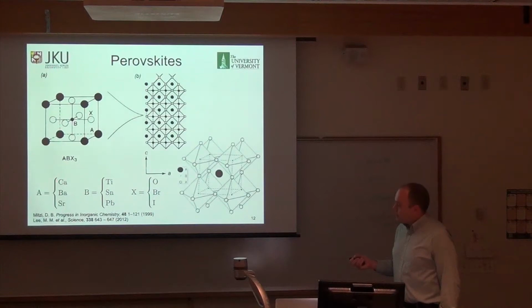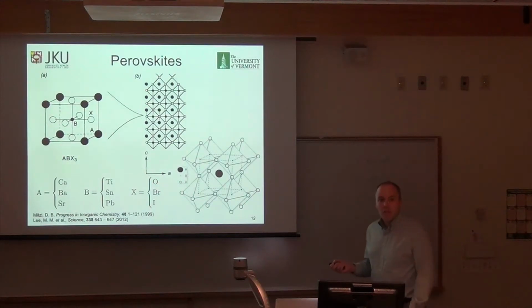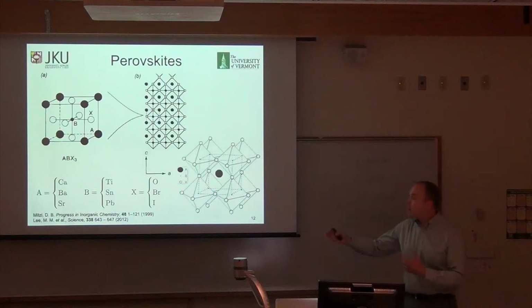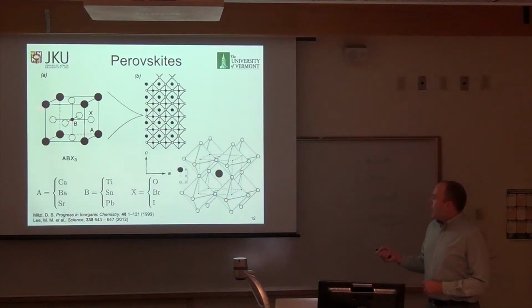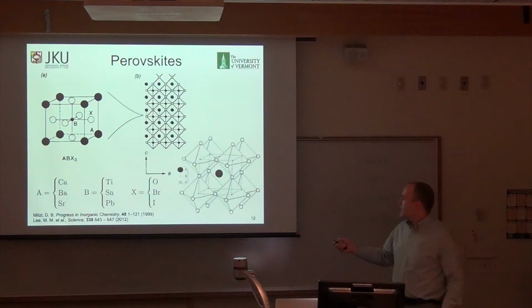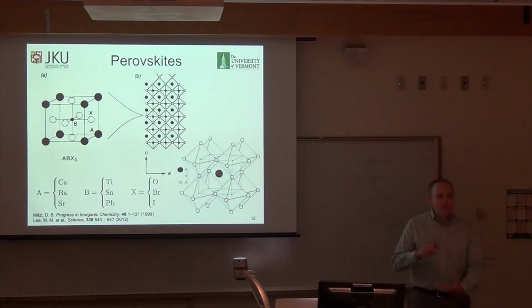So this CaTiO3 was the first perovskite discovered, but any of these combinations, and any combination including a whole lot of other things, can follow this perovskite structure. What you'll notice is that you have this BX tetrahedron, or octahedron, that forms, and the octahedra form this kind of rigid structure, leaving a void in between where the A cation sits. You can vary that A cation and it sits in the void.